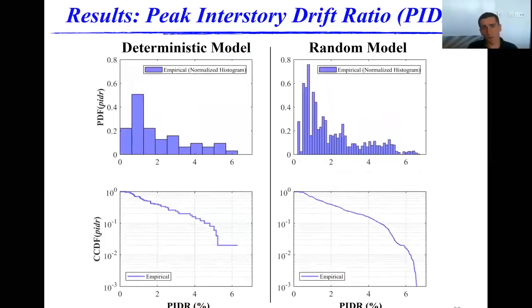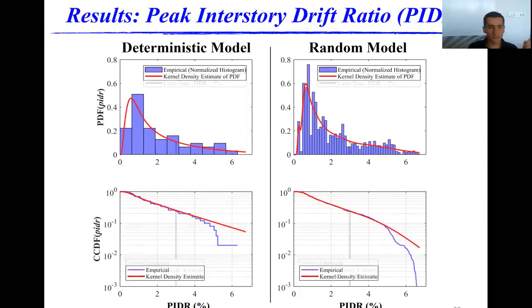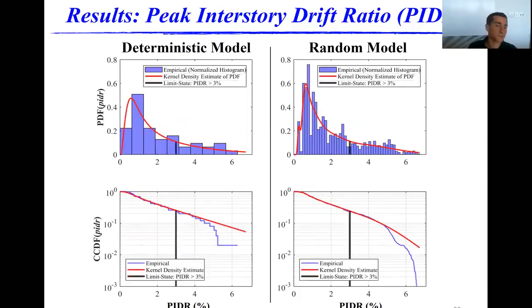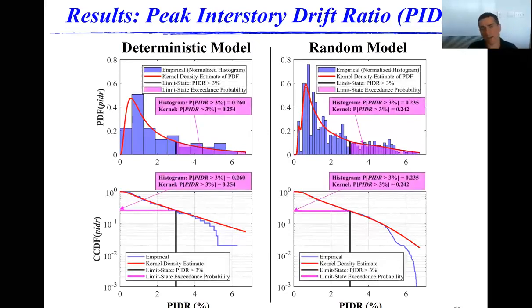I did the same thing with the peak interstory drift ratios. I selected a limit state of 3% on any story, and again, we can flesh out that area on the upper tail, or we can read off the complementary CDF values. And here we see that the values are in much greater agreement. This is likely due to this not being as high of a fractile as on the previous plot. Now we're dealing in the 26% range.